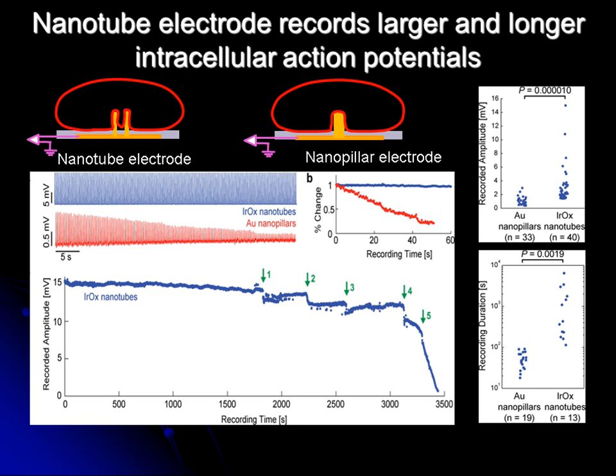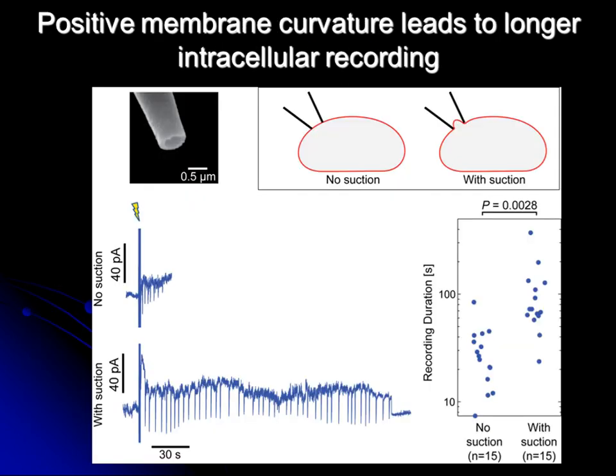And of course, one of the key questions is why nanotube electrode gets so much better performance than nanopillar electrode. If you look at the diagram of the nanotube electrode, there is a piece of membrane wrapping around the outside. There is a piece of membrane growing inside. Those two pieces of membrane have opposite curvature. The membrane wrapping around outside, we call negative curvature. The membrane growing inside the nanotube, we call positive curvature. On those different curvatures, they have very different protein composition. And so we think if the nanoelectroporation creates pores on the positive curvature membrane, it will seal much slower than the pore on the outside membrane, which is negative curvature.